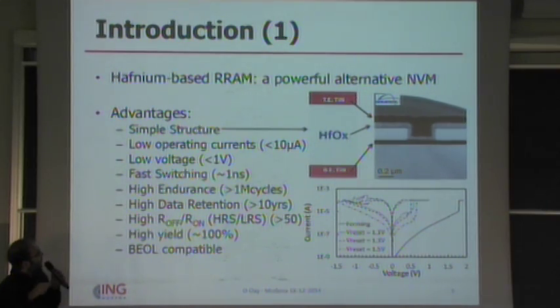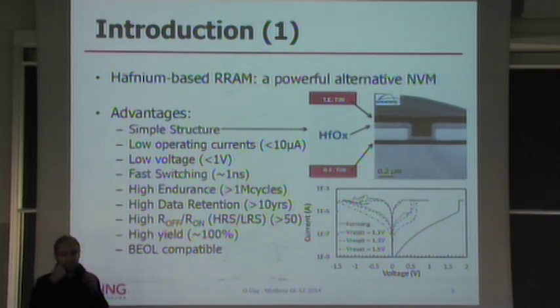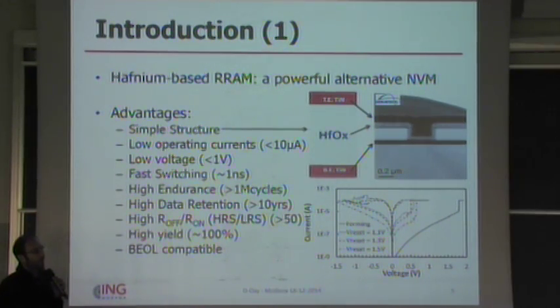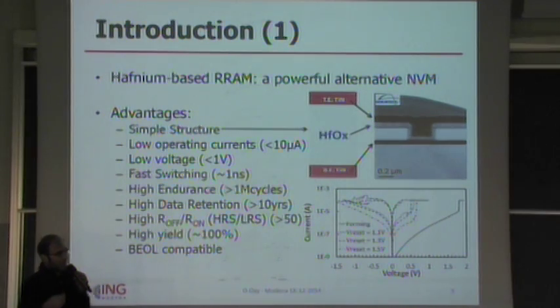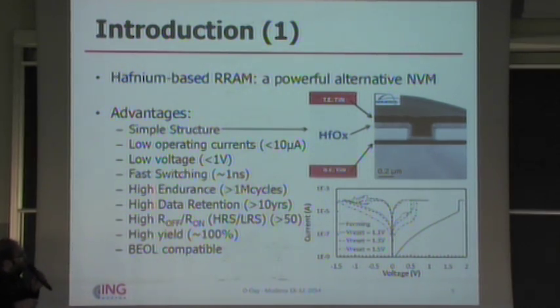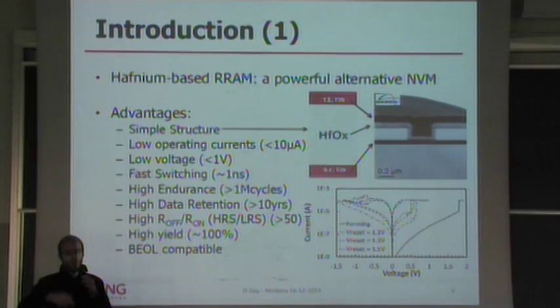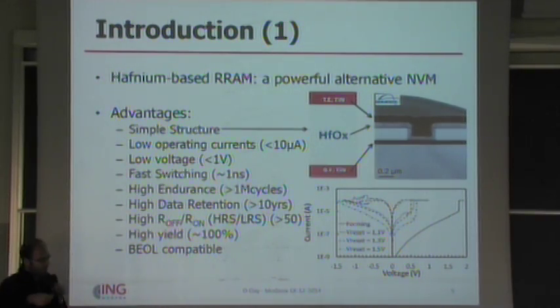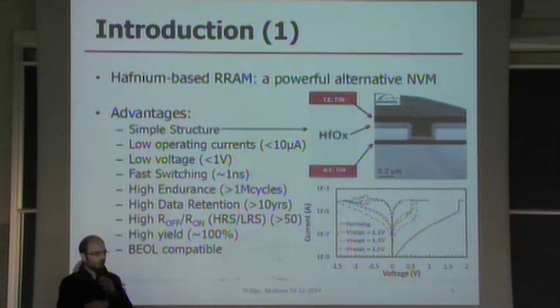It's a good memory because we have low operating currents and voltages, which will pave the way, I hope, in the future for a few femtojoules per bit operation, which is quite a remarkable result for integrated memories. They have satisfactory endurance. They are very fast. They have a high yield on the wafer. Most importantly, they are fully compatible with the standard CMOS back end of the line, so we can build integrated high-density memory in the same chip that we use to process the information, which is kind of good. It will speed up the most important bottleneck of computing machines, which is that logic and memory are separated.